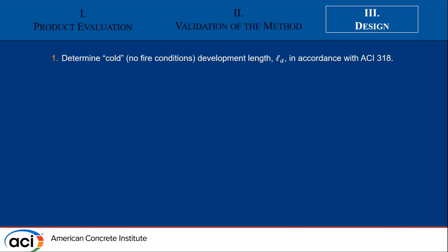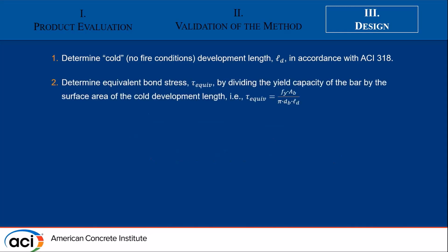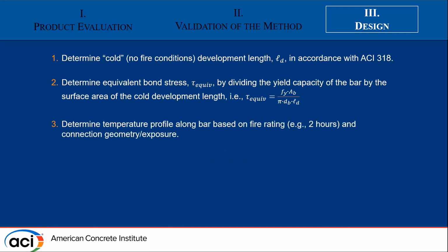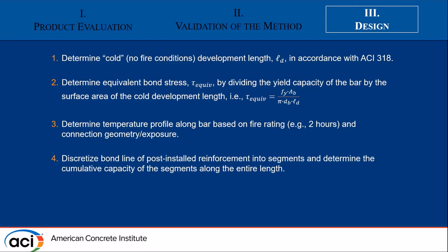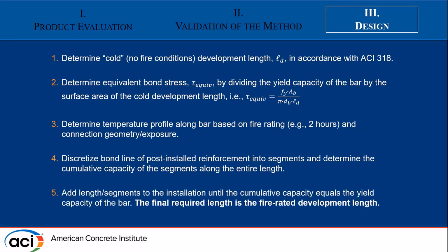The steps to actually do this in the US would be first to determine the cold development length using ACI 318. Then to use that development length to come up with an equivalent bond stress along the entire length of the bar. Determine your temperature profile for whatever your fire load is, whether it's prescriptive based on the time or performance-based design. And then, of course, using your geometry as an input. Then what I think will be the most common way to do this would be to discretize that length and come up with the individual contributions of bond along the length of the bar, and then add lengths until you reach the yield strength of the bar.